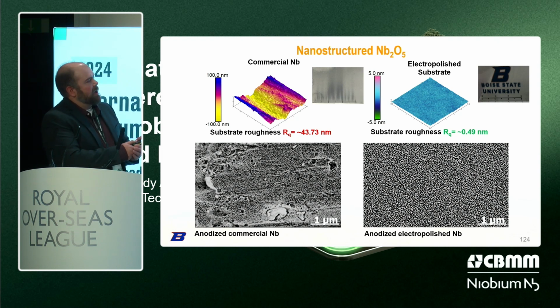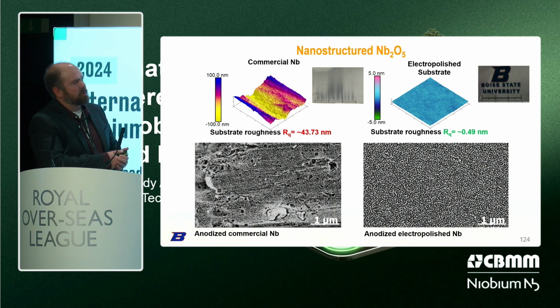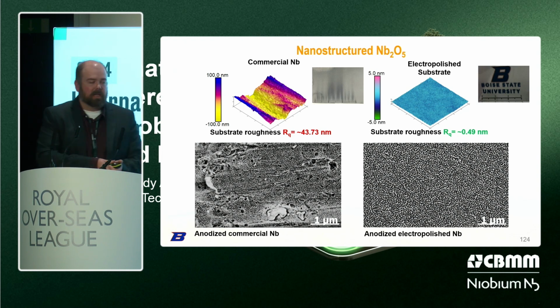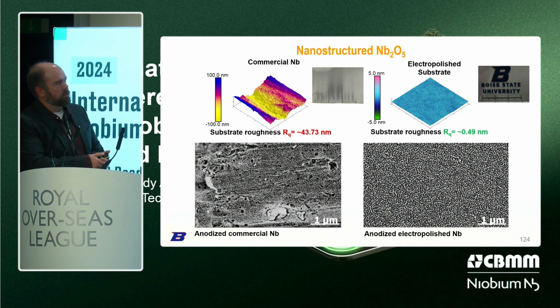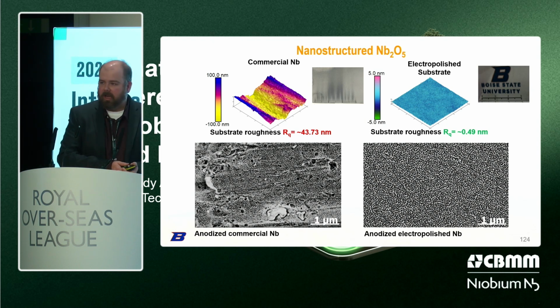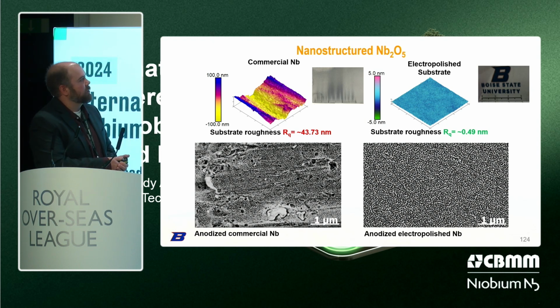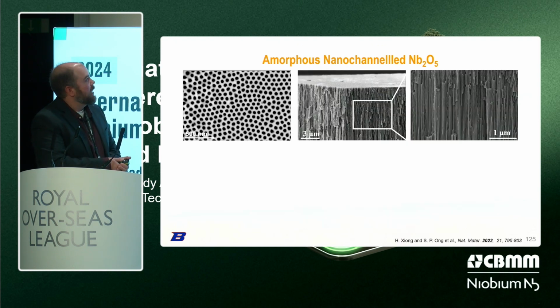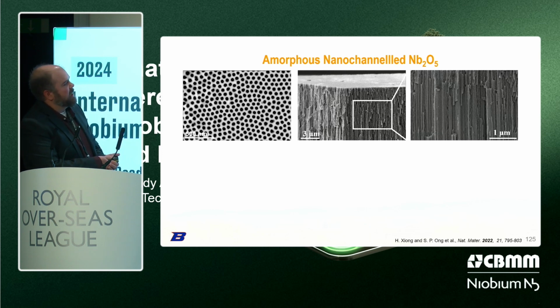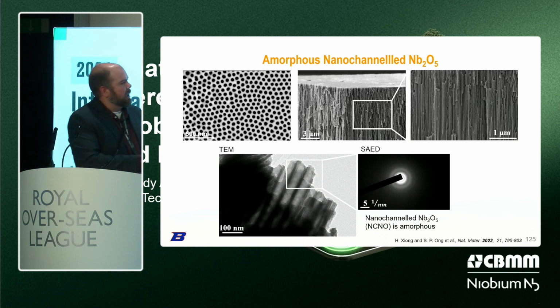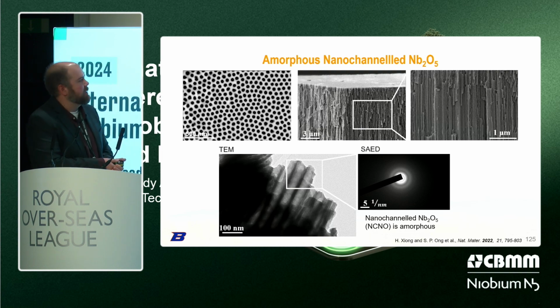I was surprised that this has actually reached way beyond the field of batteries now, into supercolliders and stuff like that. There are papers out there that have this method as one of the ways they want to do it, which we accomplished with a low temperature sulfuric acid and methanol electropolishing. If we take a little bit off the top, we can see very uniform structures throughout the niobium oxide. They end up creating this amorphous, what we called NCNO, or amorphous nanochanneled Nb2O5.